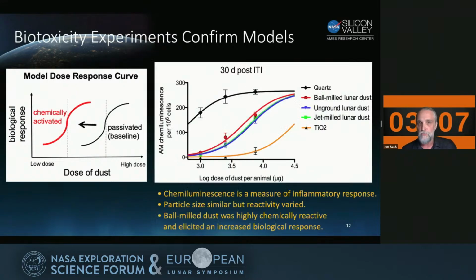And this is in fact what we observed in a series of animal studies in rats, where we injected small doses of lunar material from the Apollo 14 field site into animals. And we used 3 different preparations of lunar material: ball milled, unground, and jet milled, 3 different preparations of the same material. It was particle size controlled. Roughly about 2.5 microns or so was injected into the lungs of these rats.